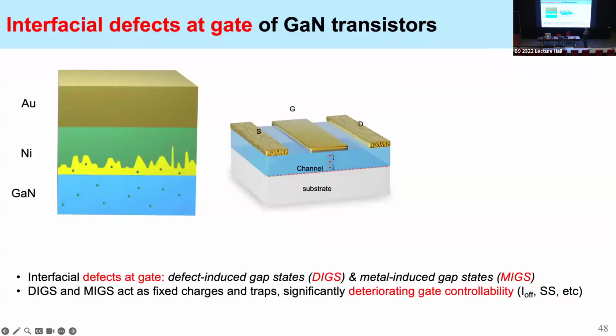So what actually affects the leakage of gallium nitride transistors? Mainly, we have several interfacial defects at the gate that can impact the leakage, where it will increase the leakage. Those are the defect-induced gap states, DIGS, and metal-induced gap states, MIGS. And they are largely created because the conventional metal for the gate, nickel and gold, has direct contact with the gallium nitride, right? Those defects and gap states will act like traps and charges that will basically deteriorate your gate controllability. So that will increase your off current, I_off. Basically, this is the leakage. And it also slows down the turning on and off of the transistor, which is called subthreshold swing.